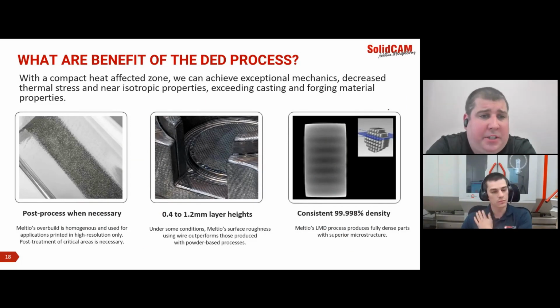And overall with this process, we have a lot of benefits. So a lot of questions that I get is what's the resolution or how much overbuild you need to allow for machining. And it is somewhat feature dependent as well as part size dependent, but as a general rule, about 1 millimeter or 40 thousandths per side is how much I will overbuild and then machine to final net shape. Now, as you get into larger features, parts that are multiple feet in length, you may need to add more material, or if you have a more complicated 3D surface, you may need to add up to 1.5 millimeters or 60 thousandths of an inch, but certainly not an excessive amount of material.